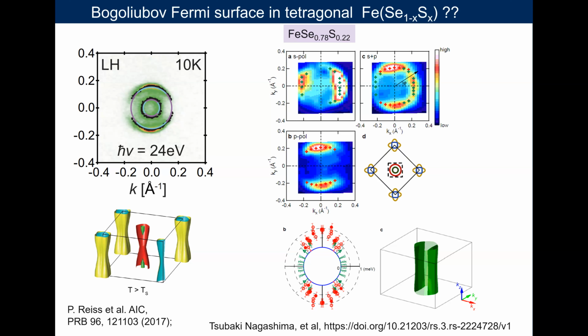And these are our tetragonal Fermi surfaces showing the whole Fermi surface, which in my view bears the same signatures as in the tetragonal phase of iron selenide. Whether these effects also occur on the other bands, or how exactly this might manifest for other pockets, remains to be understood.